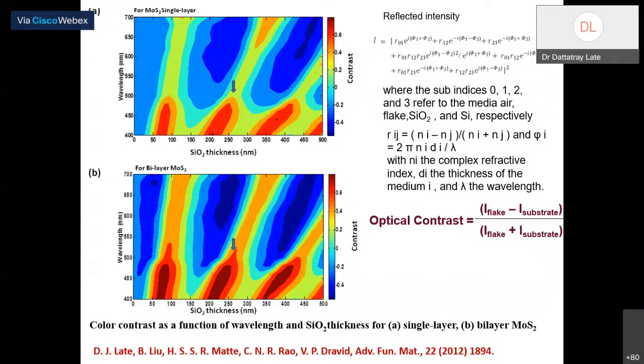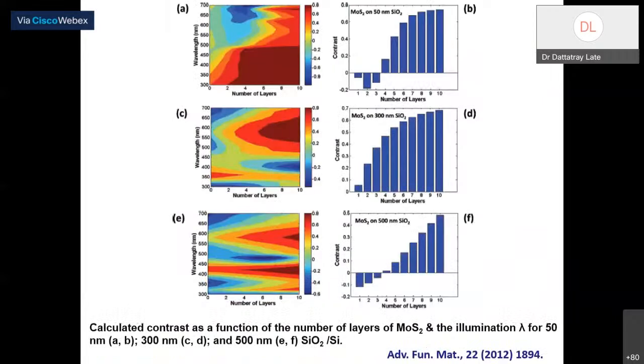But we should know these simple parameters: the refractive index of air, of that particular material, SiO2 and silicon. You can put these parameters in and simply calculate the color contrast, the optical contrast, of that particular layer. These are simple calculations done as a function of number of layers and wavelength. You can see this is for 50 nanometer SiO2, or 300 nanometer SiO2, or 500 nanometer SiO2, and you can get back the expected color contrast of that material.